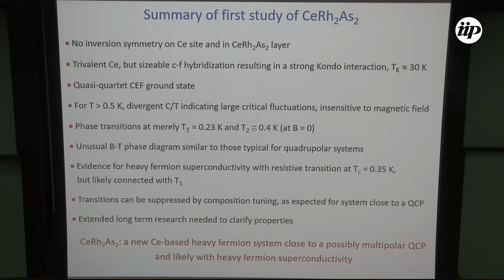We have 2 phase transitions, one very clear at this temperature, and a second one less clear, but still clearly present in a number of samples at this temperature. We have a very unusual phase diagram in the sense that this transition for the field in the basal plane strongly increases with applied magnetic field. We have a first preliminary evidence for superconductivity, with a transition at this temperature, likely connected with T1, but that has to be proved. The transition can be suppressed by composition tuning, as expected for a system close to a quantum critical point. We expect that this system will give us work for at least the next 5 years. And that is the conclusion of my talk, and I thank you for your attention.